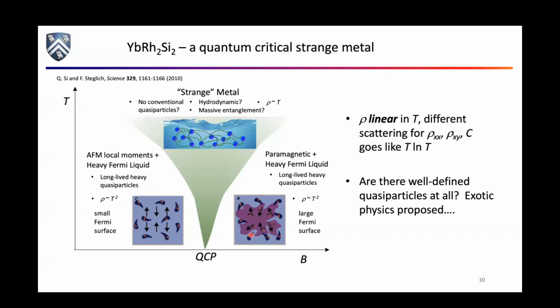And then on the other side, on the high field side, you disrupt the antiferromagnetism, and you now have a large Fermi surface. And again, you have quasiparticles that are heavy. But the point is that on either side of this critical point, the system's a Fermi liquid. But in the middle, where the system in some sense doesn't know which electrons are really fully participating in the metallic state, the system is a strange metal, right? You have rho going linear in T, you have all this other phenomenology I just mentioned.